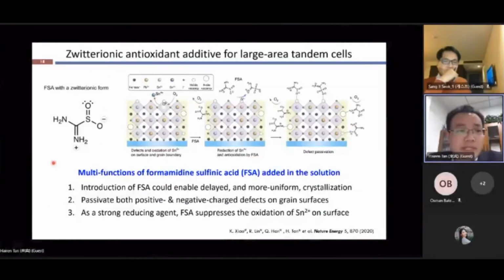So next, we carried out another work, where we add some additive in the precursor solution so that we can modulate the crystallization process, and also passivate the defects on the surface and the grain boundaries. What we choose is a kind of zwitterionic molecule. We call it formamidine sulfinic acid. We add a very tiny amount of this additive in the solution. Because it has a sulfinic group and also a formamidine group, these molecules can coordinate with the metal ions, so that it may enable a delayed and more uniform crystallization.